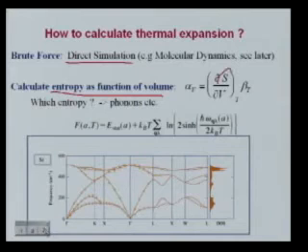And so the way you would calculate the entropy, if you're only going to deal with vibrational entropy, is by calculating the phonon density of states. So literally you would look at the quantized vibrations, do the statistical mechanics on them, and those of you who've taken 320 may remember this, and calculate the free energy associated with these phonons. And I'll say a little more about this later. For example, this is the phonon spectrum for silicon. So you can actually quite accurately calculate it.